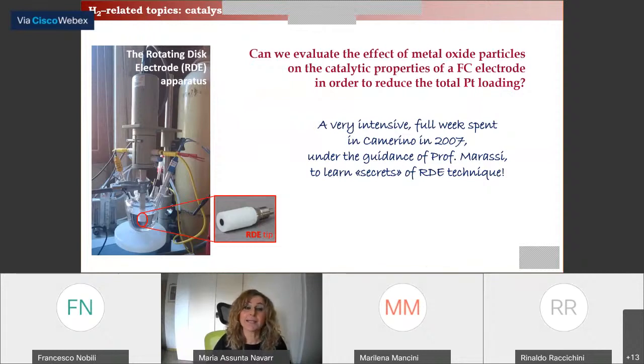Besides the polymer membranes, we are also interested in the catalyst materials for fuel cells. And we were wondering if our metal oxide particles could have a catalytic effect to be used as electrode component in order to reduce the total platinum loading. As you know, such catalytic properties can be conveniently investigated by an electrochemical technique based on a rotating disk electrode, that is pure electrochemistry.